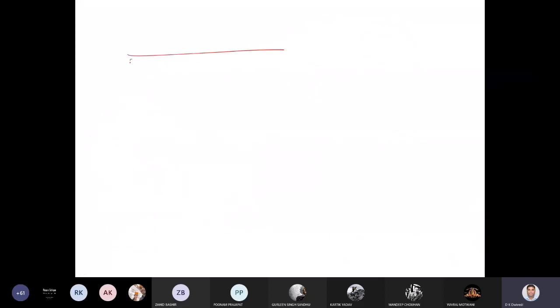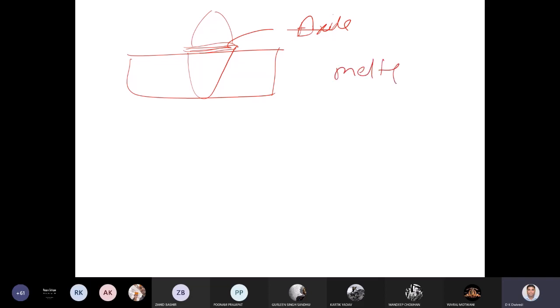And if that is happening, then what you will find, like this is the base metal, you are applying heat through the arc, and alumina is being formed, or titanium oxide or chromium oxide is being formed. It will form a reaction oxide layer. So let's say the oxide layer, which is refractory, is not melting easily. So it will interfere with the melting of the base metal, as well as it will not get melted itself, so it will be there as oxide inclusions.